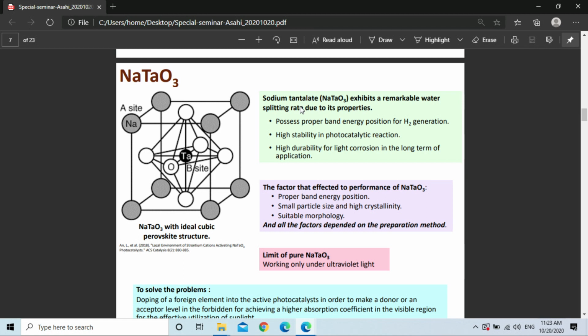It can be used for a long time. But more than the band structure, we also have to consider the size, morphology, and crystallinity of the semiconductor. These parameters can be controlled by the synthesis process. So in this work, we select the hydrothermal process, which is a low temperature process, and we can control the size, morphology, and shape of the particles at low temperature compared to solid-state synthesis.